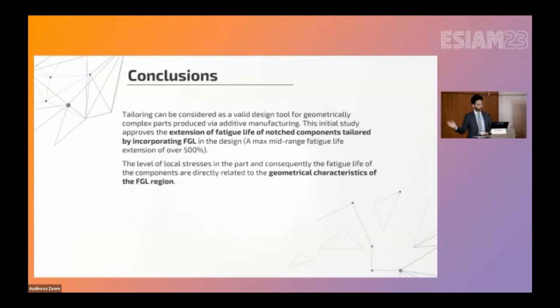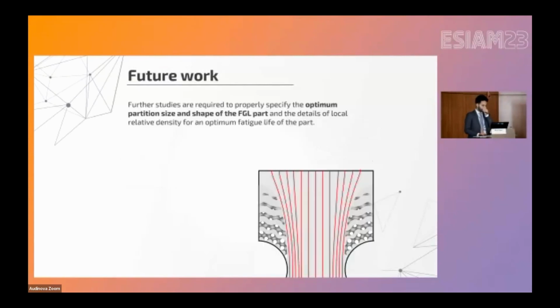Of course, for this specific material, again, it's a polymer. We are working on metallic samples at the moment. The level of these local stresses at the notch root of this tailored design very much depends on the morphology of the functionally graded part of the sample. There are some parameters that need more study instead of randomly selecting them: the partition shape, the gradient orientation, the relative density, and the boundary conditions. So these are the things that need further evaluation.